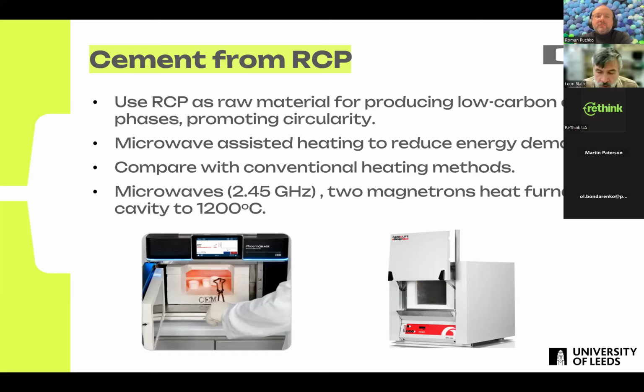One of the reasons why cement has such a high carbon footprint is that one of the raw materials used for its production is limestone. And when you take the limestone and blend it with clay, heat it up to 1400 degrees, you produce cement. But that heating process, as well as the energy, gives off carbon dioxide from the breakdown of the calcium carbonates of the limestone that is used to make cement. If you use recycled concrete powder, you no longer have that CO2 that's given off during production. So you can significantly reduce the carbon footprint of your cement production.